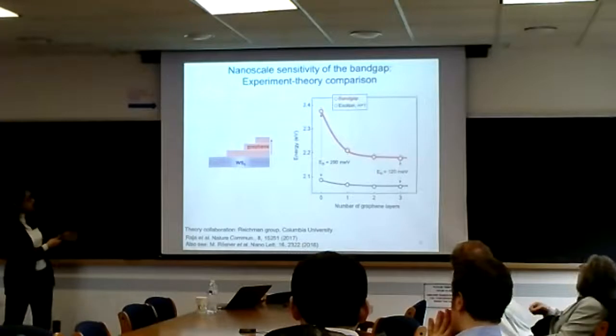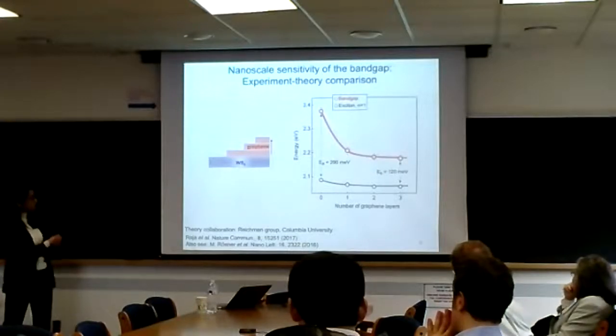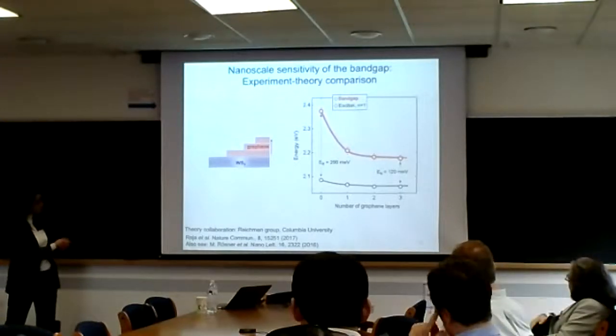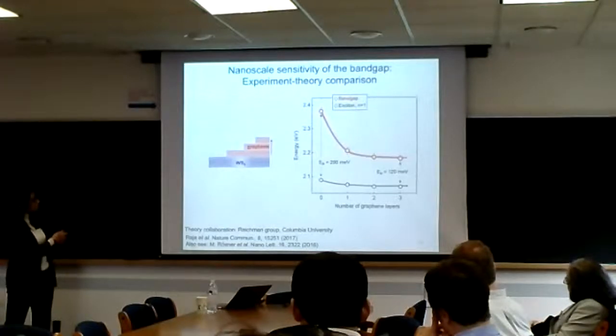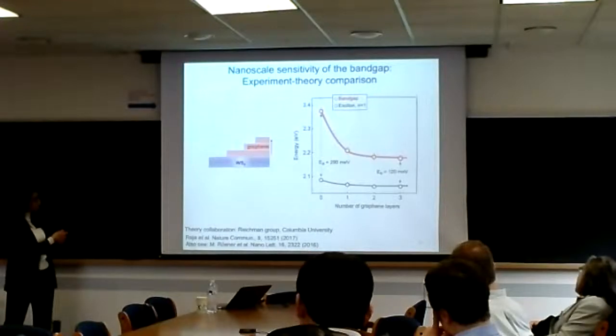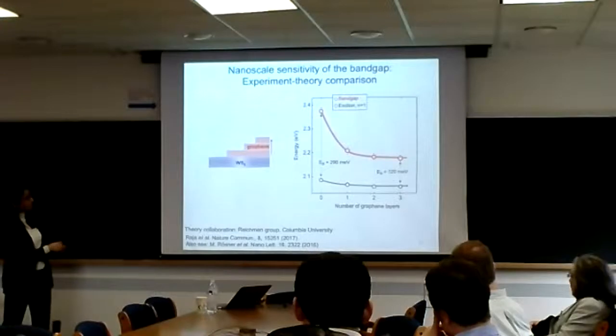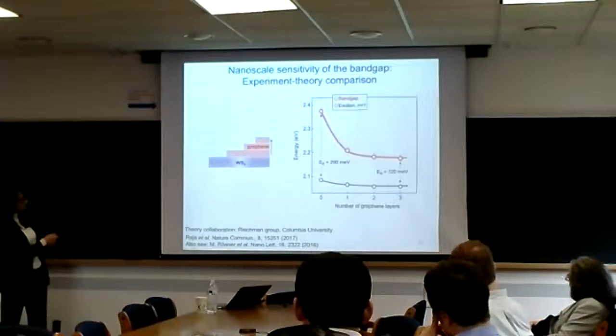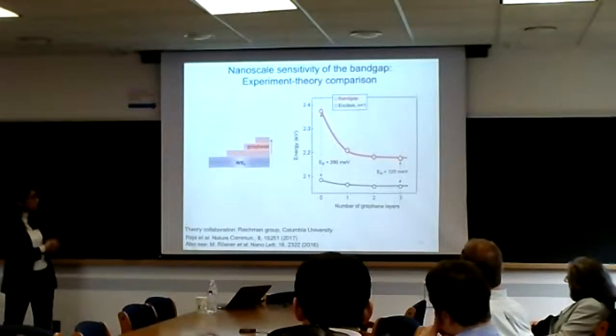Now, to move away from that picture, now we have the theory, we can actually plot it directly on the energy scale. So we have the 1s, this is experimental data that goes from 2.1 to a little bit lower. There's a few tens of meV change in the exciton spectra here. But if you look at the quasi-particle gap or the band gap, this changes by a lot more. So you start with a binding energy on the order of 300 meV, and you reduce down to close to 100 meV here. And this also indicates the nanoscale sensitivity in the out-of-plane direction. So we still don't know how sharp it is when it changes in the in-plane direction.